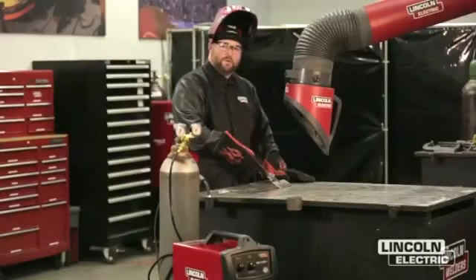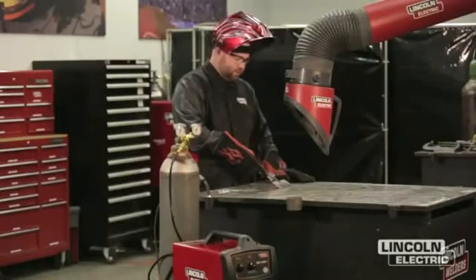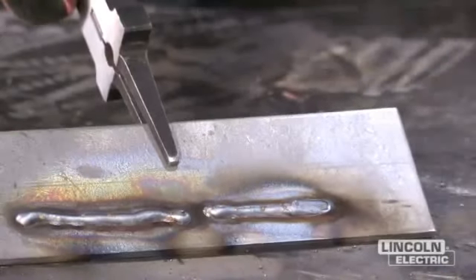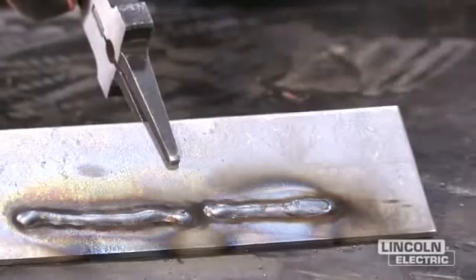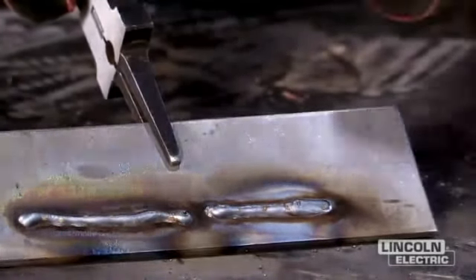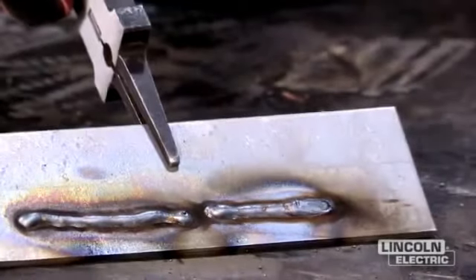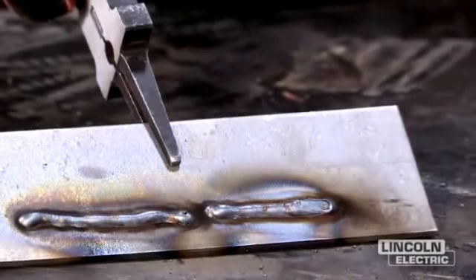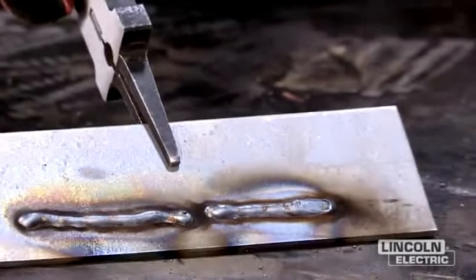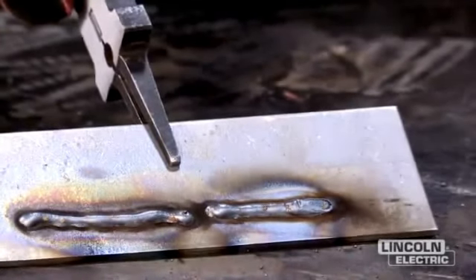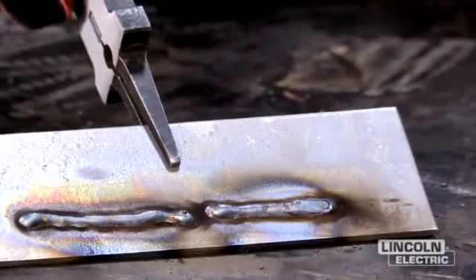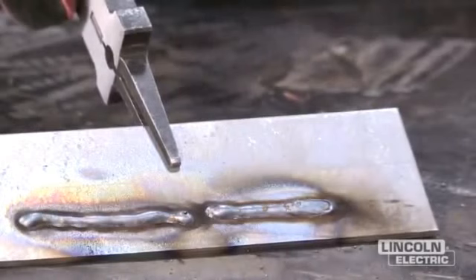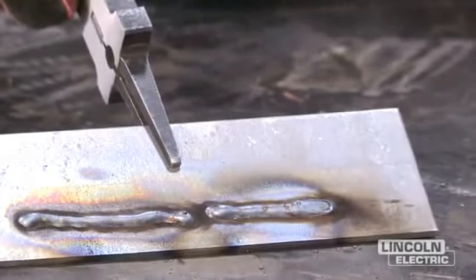So we just made a weld with a contact tip to work distance too short. And you can tell a couple different things. One is right here at the end, you can see where my nozzle actually drug on the top of the weld bead. The other thing is it's really hard to see the puddle and to follow the joint when you're welding on a joint. So make sure we try to maintain that roughly 3/8 of an inch stick out, and then we'll be able to make a lot better weld.